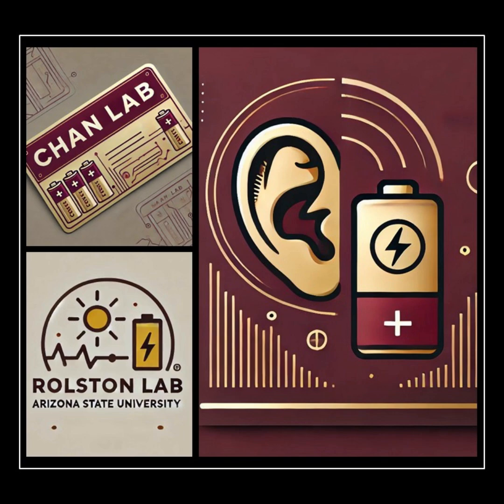So how rapid is rapid in practical terms? The research we're looking at today found a measurable layer can form in, get this, as little as 3 minutes of air exposure. 3 minutes. Seriously? Yeah. Think about it. You step away for a coffee and your electrolyte is already starting to get contaminated. It just shows how pervasive this problem is.